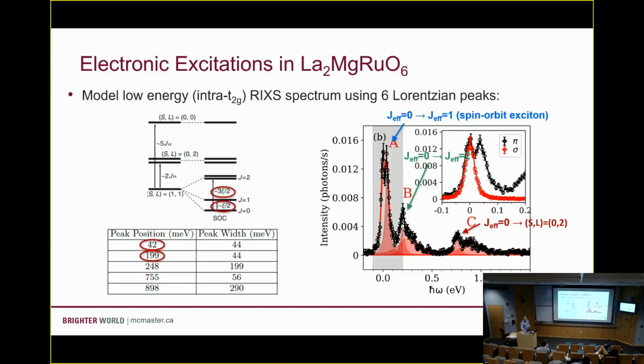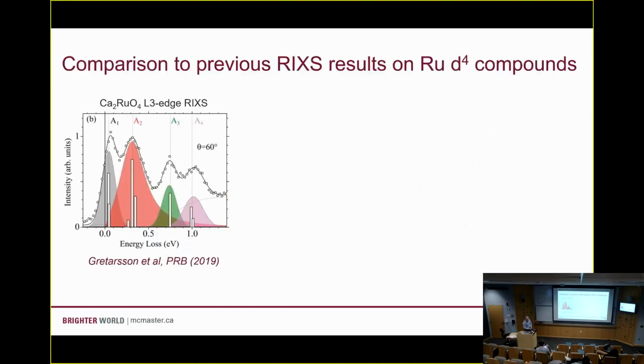Okay, all right. So if you're looking closely at these numbers, you'll see there's a slight complication. If we're really in this strong coupling limit, what we'd expect is peaks A and B here should be at a 3-to-1 ratio, whereas what we measure in practice is actually about 5-to-1. And this is because we have some other terms that are entering into our single ion picture that are complicating things a little bit more.